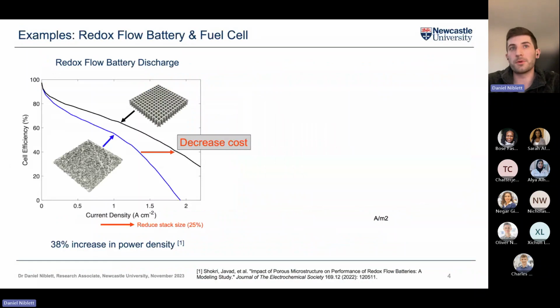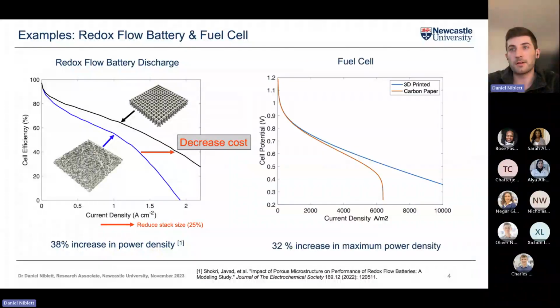And there's a couple of examples. Generally, these are simulation examples. So a redox flow battery discharge. On the figure seen here, you want to be as high as you can on this figure. So the black line is what you would get if you use an ordered structured material for a gas diffusion layer in a redox flow battery. And if you replace the traditional materials, you can get about 38% increase in power density.